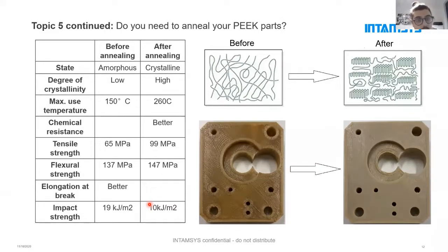So if you go for jigs and fixtures, high precision machine automation jigs and fixtures, also amorphous PEEK can be a good idea. While they are more resistant from the impact strength and still very stiff, they still have a high tensile strength of 65 megapascal, which is more than 50, 60, 70% of all materials in FDM printing.